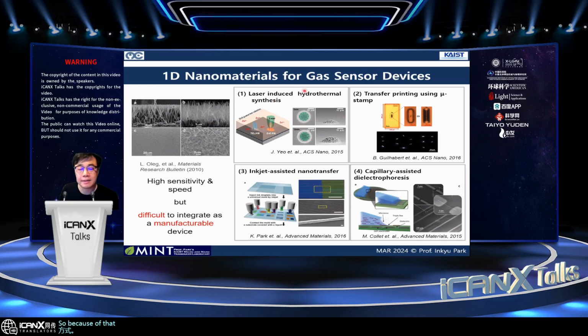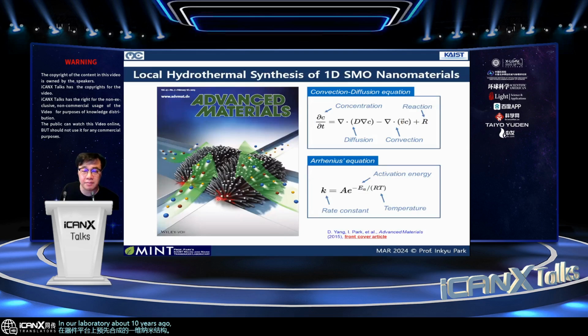manner. So because of that, a lot of people have developed techniques to directly integrate or align these one-dimensional nanostructures on the device platform using laser-induced local synthesis of metal oxide nanomaterials, transfer printing using microstamp, inkjet assisted nanotransfer, or capillary assisted dielectrophoresis to align these pre-synthesized one-dimensional nanostructures on the device platform. In our laboratory, about 10 years ago, we developed a technique called direct and local hydrothermal synthesis in the hydrothermal precursor environment.